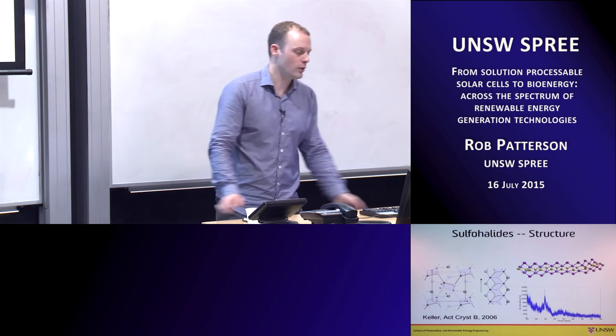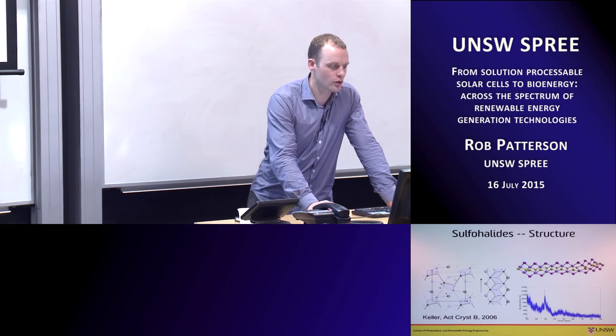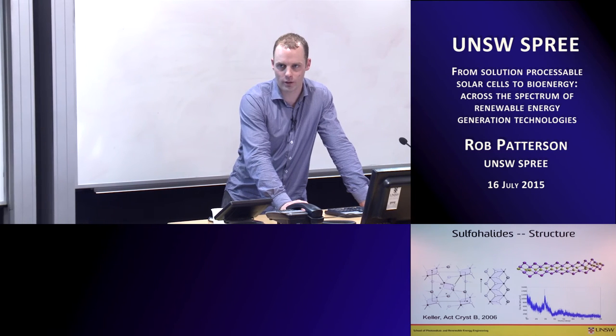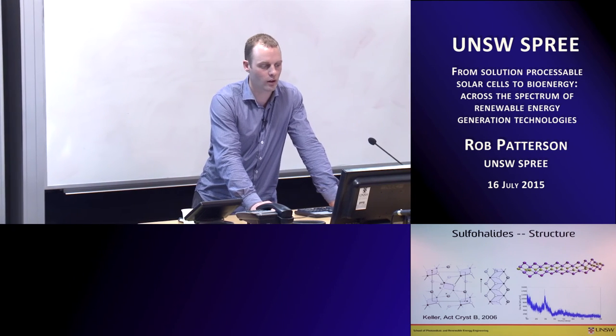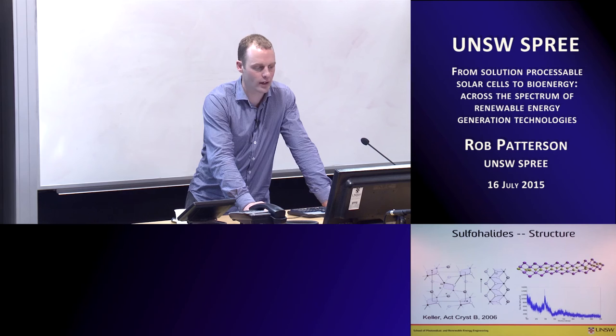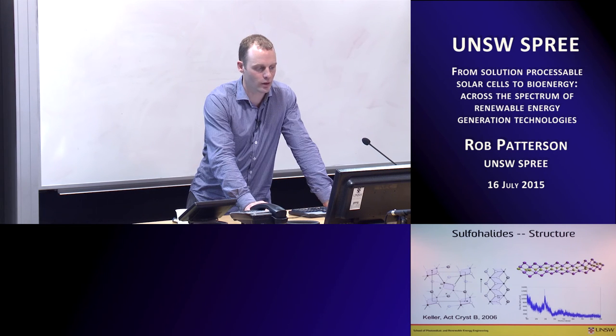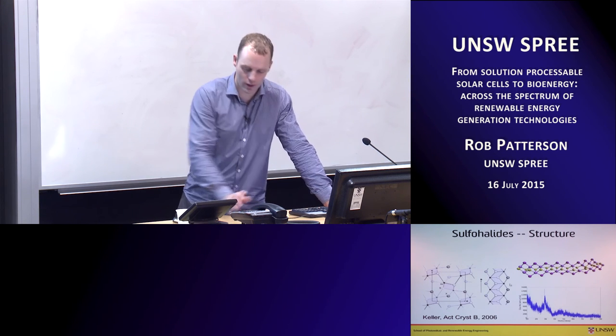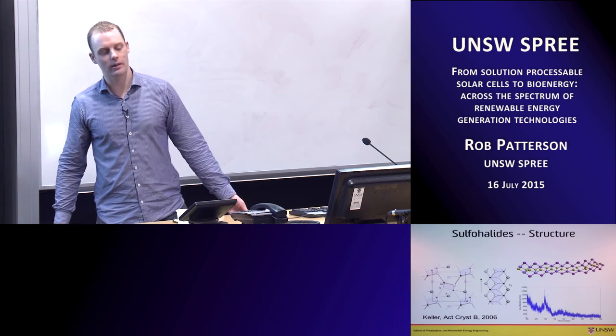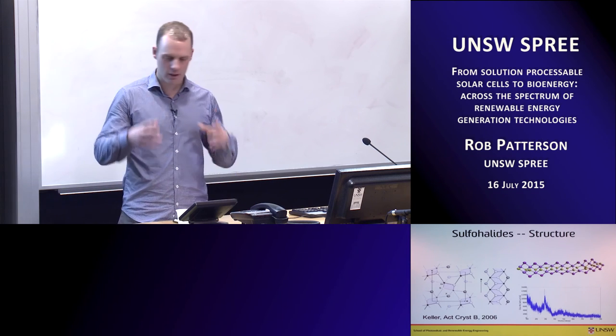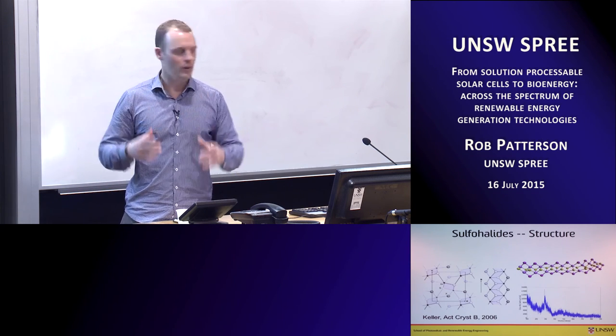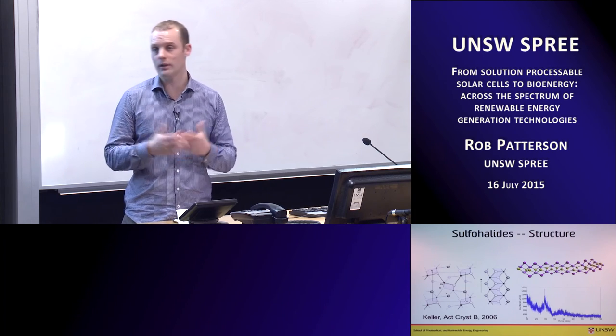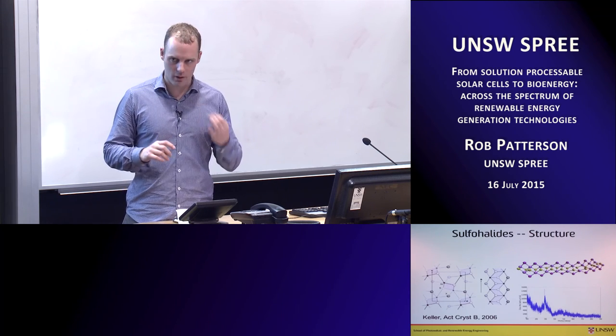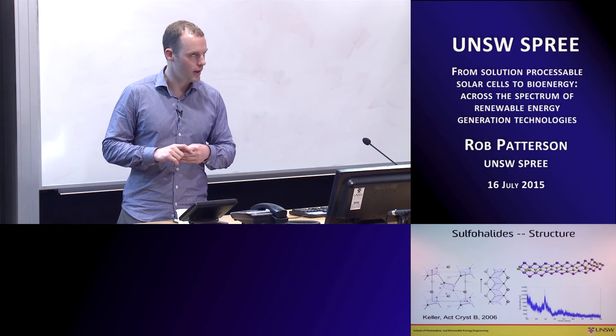But one of the things that you can see immediately is that there should be strong anisotropy in the material in terms of the conductivity and transport. Along the length of the nanowire, you would expect better transport than across the diameter. And this is also probably true for any elastic constants of the material. So any tensors associated with how the material deforms and the electric fields that result from that are probably also very anisotropic.